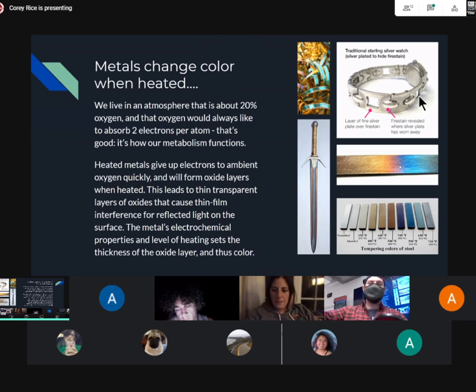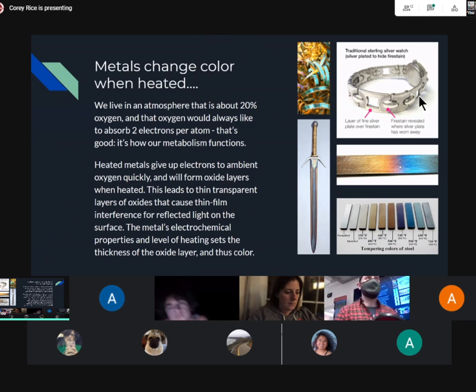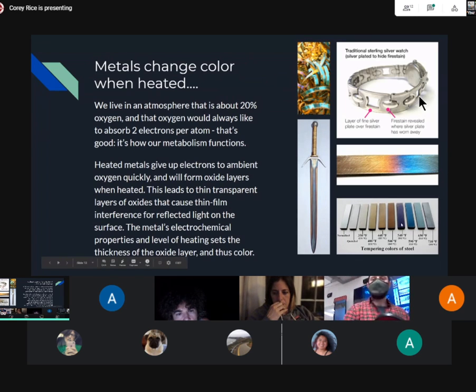What happens with that, and why you get the color, is that light comes in, hits the metal, bounces through that little rust layer, and only one color is constructively interfered as it comes out. And it's based on the actual geometric thickness of the layer. So you get these different layers of rust that show up based on temperature, but that's based on the depth that the oxygen is able to permeate into the metal, and thus the thickness of the semi-transparent rust layer,